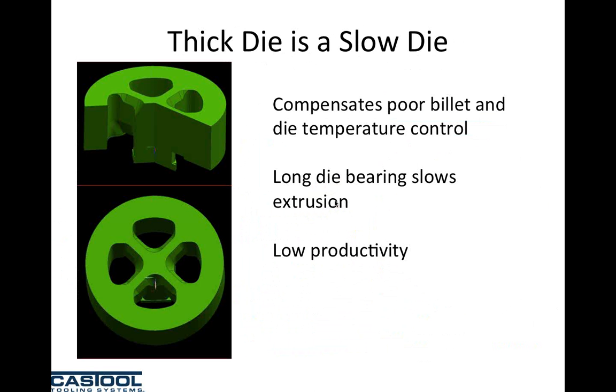If they were given a thin die with open ports with short bearings, there wouldn't be enough material for them to control the die. The problem is a thick die with long bearings is a slow die. A slow die is a die that requires a hot billet temperature and is going to end up having a rather slow ram speed.